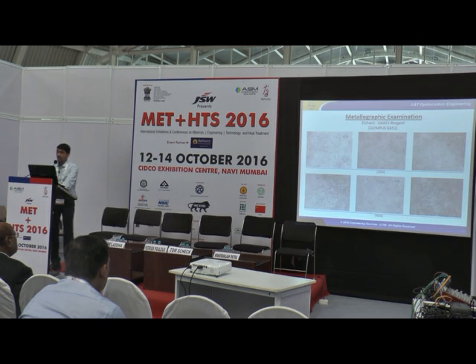When etched with Vilella's reagent, the component revealed a mixed or non-uniform microstructure of martensite, untempered martensite, tempered martensite, as well as retained austenite. So it was a very non-uniform microstructure seen across the cross section of the axle component.